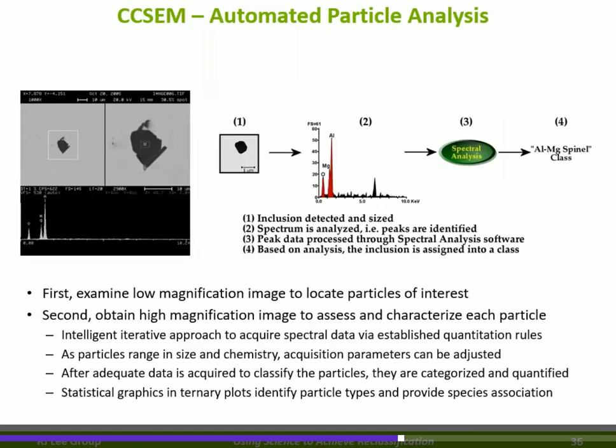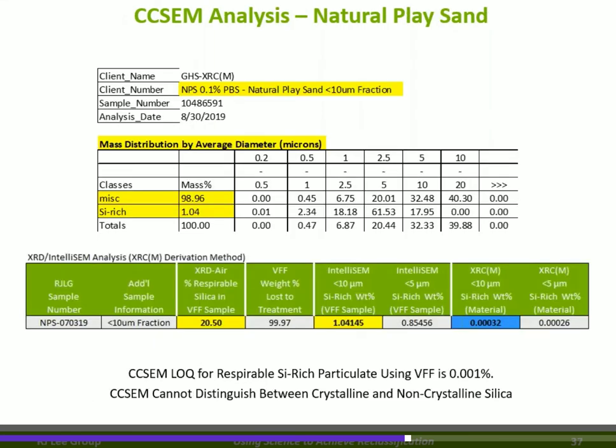We want to know if the crystalline silica in that respirable fraction is free and bioavailable, or actually bound up and impure. For that, we're going to go to CCSEM with IntelliSEM. The way CCSEM works, it's a sea of particles across the filter. It comes up against a particle, detects the leading edge, goes into analysis, determines the size of that particle, and determines the elemental content. What we want to know is how many particles in the size fractions less than 5 and less than 10 are actually SiO2. When we do that, we find that only 1% of the particles in the fraction less than 10 are SiO2 rich. In other words, they're not contaminated with other materials.